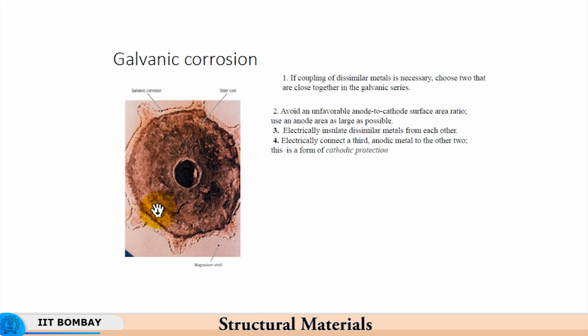So, what it means is that if the anodic area is very, very large and the cathodic area is relatively small, then the current density is something that is very important. If the area of the anode is large, so the anode to cathode surface area ratio is high, then the current density is that much lower, and with a lower current density the rate of corrosion is also lower. On the other hand, if the anodic area is very small and the cathodic area is very high, in that case the rate of corrosion is high because of a very high current density, the same amount of current concentrated in a very small area.